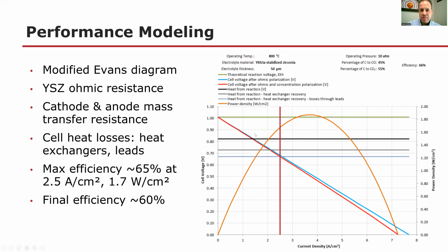This also shows the theoretical heat from the reaction. This is with some carbon monoxide generation, and then we lose some amount of heat to the gases going out. We recover some of it with a heat exchanger. And finally, we lose some energy through the terminal leads on the fuel cell stack. So this shows those losses. Nonetheless, even with all those losses, we can maintain thermal balance with 60% efficiency here.